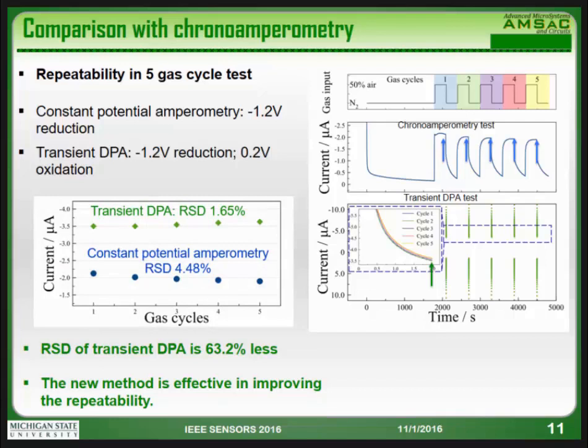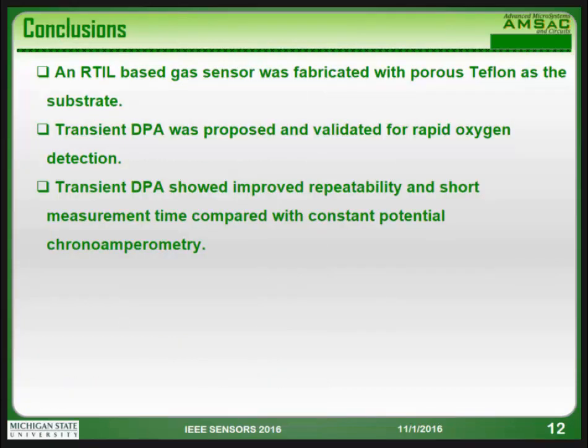The relative standard deviation of the transient DPA is 1.65%, and that of the constant potential amperometry is 4.48%, which is 63.2% decreased. So we conclude that this method is very effective in improving the reproducibility compared to the constant potential amperometry. Here is our conclusion. We presented an RTIL-based gas sensor with a porous PTFE substrate, and then we proposed this new method, and we compared our new method with a conventional method, and it shows improved reproducibility and a very short measurement time.